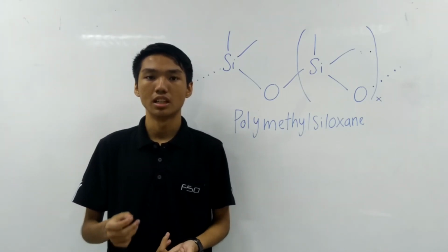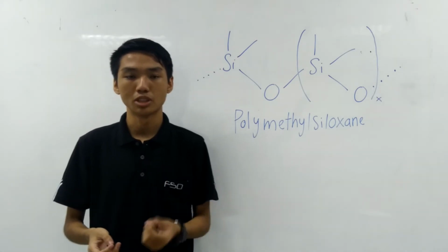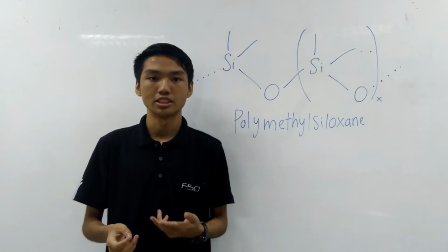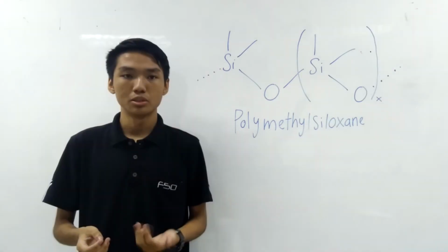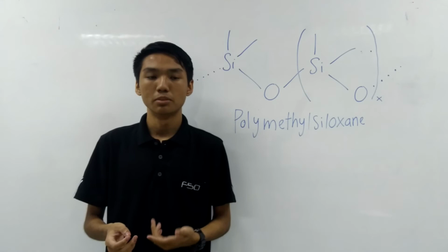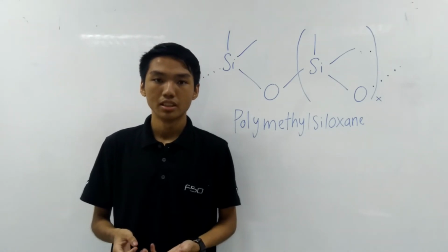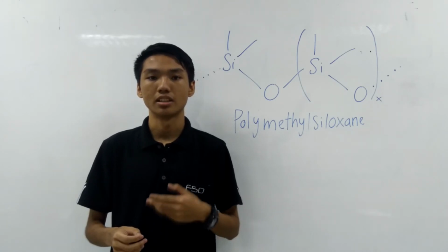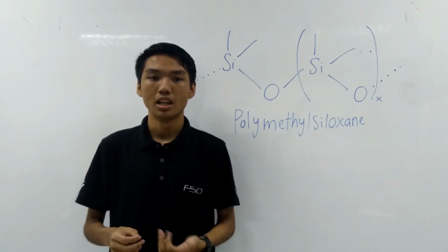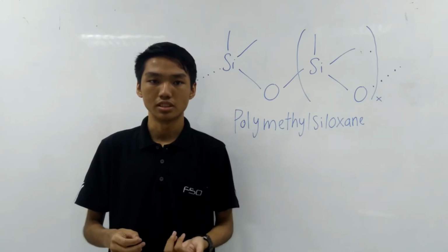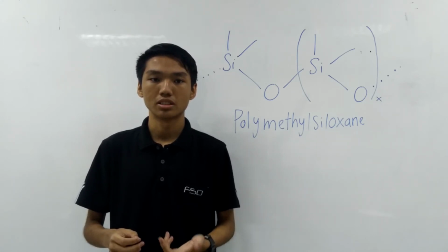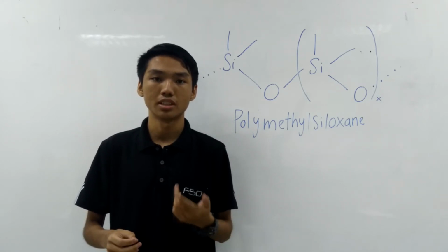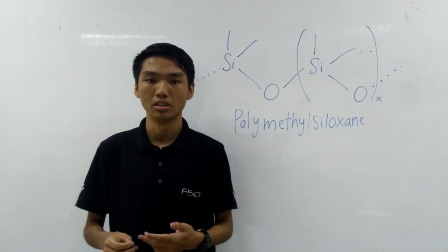The foam is countered by adding tiny amounts of anti-foam, usually silicone chemicals such as polydimethylsiloxane, commonly used as anti-foam agents. Since the materials are not very oil soluble, they can separate from the oil onto the surface of air bubbles and cause the air bubbles to rupture by reducing the surface tension. The common dosage of the anti-foaming agents is from 10 to 100 parts per million in oil.